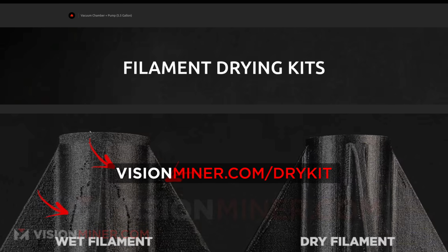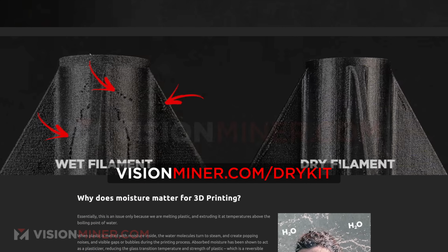Filament drying: at least 4 hours at 150 degrees Celsius. CF PEEK is highly hygroscopic, which means it absorbs moisture from the air. Wet filaments will cause bubbles, steam, and poor layer adhesion. Drying your filament before printing ensures that you will get a strong, consistent print with a smooth surface finish.